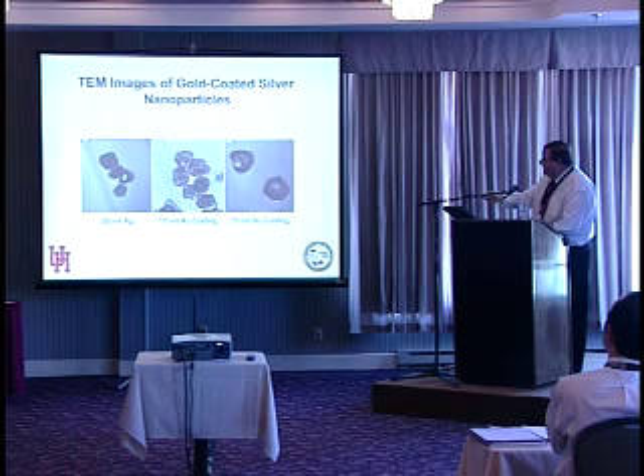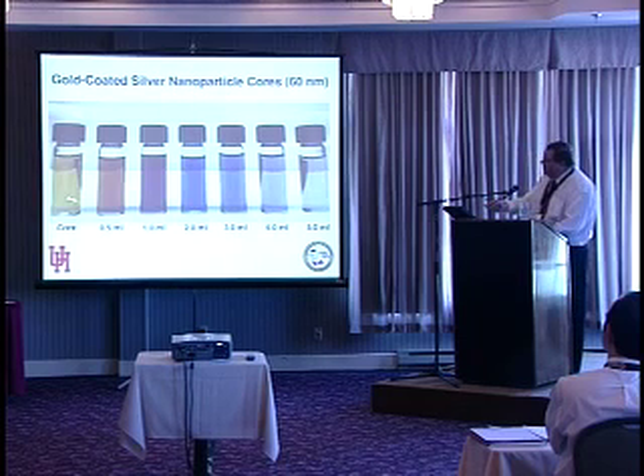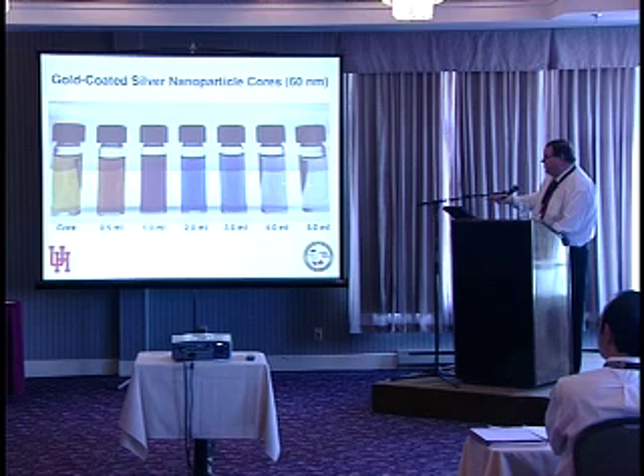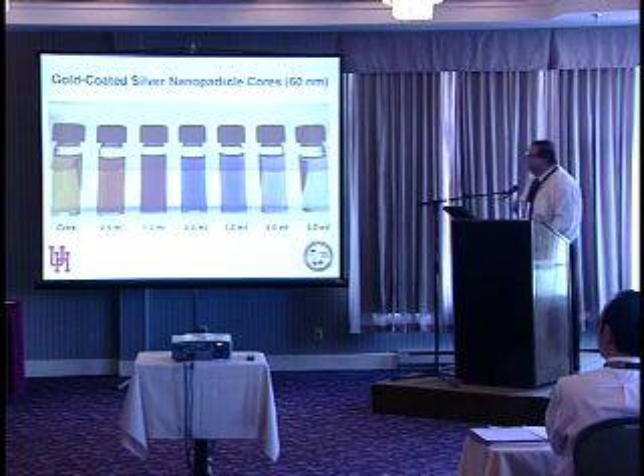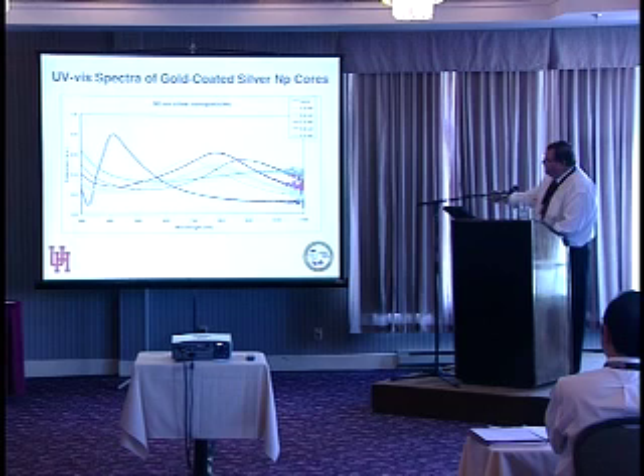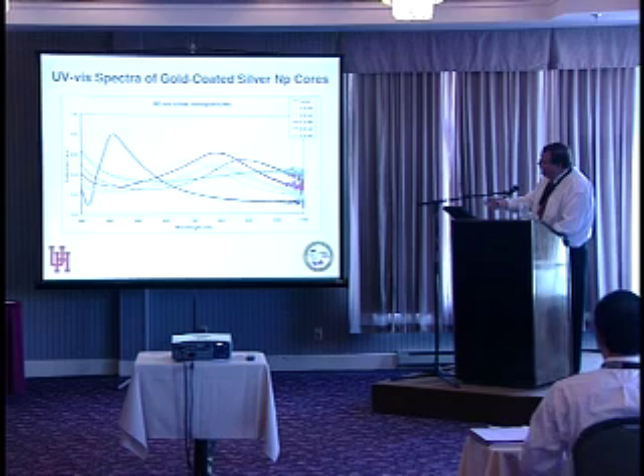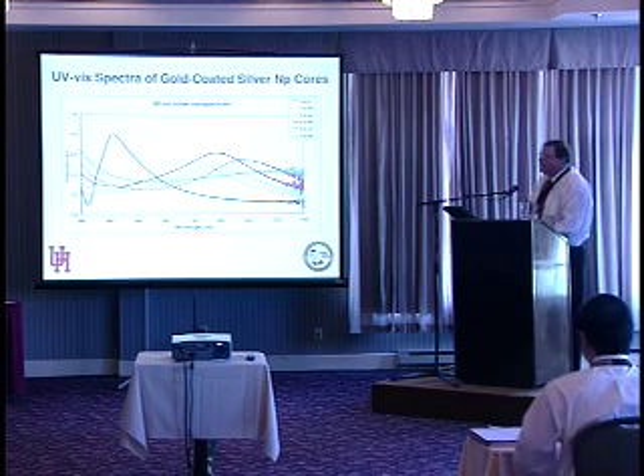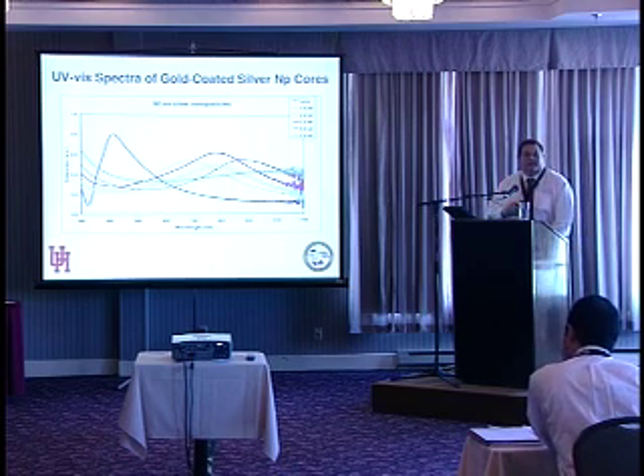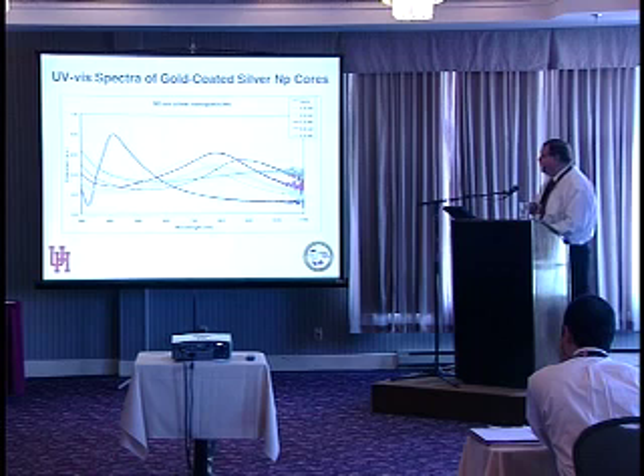So here are some TEM images of just the core particles, and then ones that have the gold coating on them. Here are an example of these particles in solution, the silver core particle, and as we grow the gold shell, we're moving toward the near infrared. Here are the UV spectra that illustrate this. A silver core particle is just above 400 nanometers, and we can vary the absorption wavelength all the way out to about 950 nanometers with this very simple and easily reproducible process.